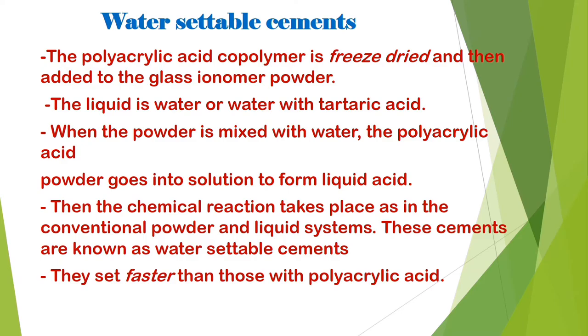In water-settable cement, the polyacrylic acid copolymer is freeze-dried and then added to the glass ionomer powder. The liquid used is water or water with tartaric acid. When this powder is mixed with water, the polyacrylic acid powder goes into solution and forms a liquid acid, initiating the chemical reaction. These cements are known as water-settable cements and they set faster than those using polyacrylic acid liquid.